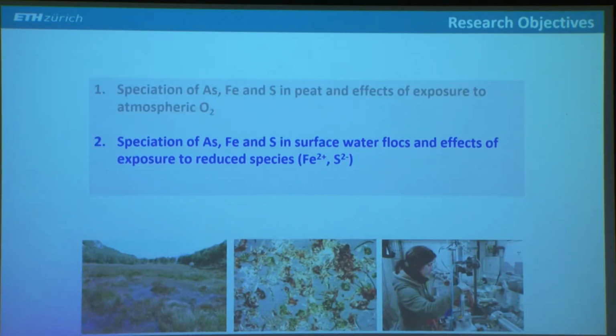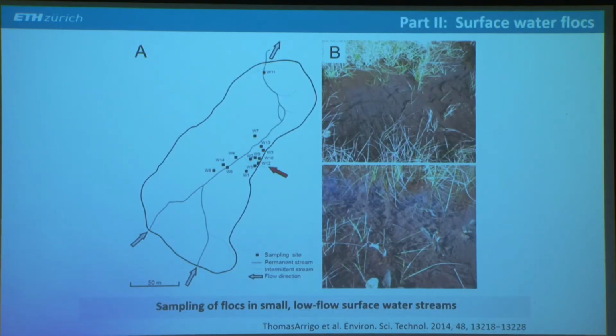So in the next part, I will show you some more recent results where we looked at these floc materials that were collected in these surface waters. So we went back to the field and we collected these iron-rich floc materials, basically just by scooping them out of little streams. We washed them and sieved them, and then freeze-dried them for characterization and used them for experiments.